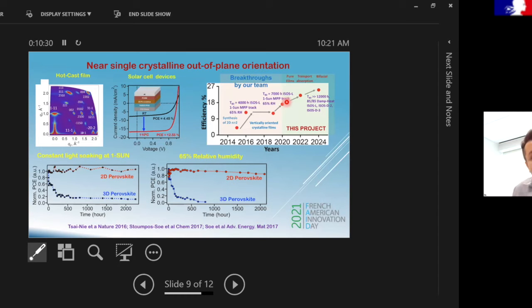We are about here. And so we have a very nice pathway of going to about 20 and 25%. And this is really important because one of the things that has limited the three-dimensional perovskites, or is limiting them, is their stability. So our approach was that if you can get the stability first and engineer the efficiency later on, then this could be a very effective pathway for getting something that is translational and a device that really works.